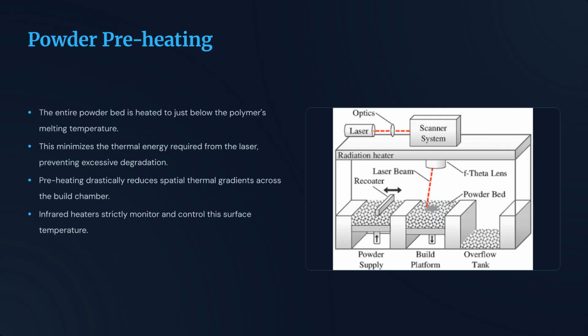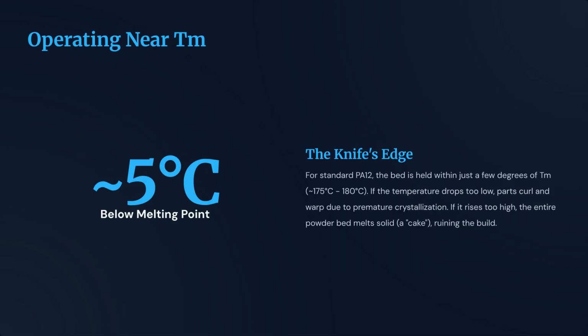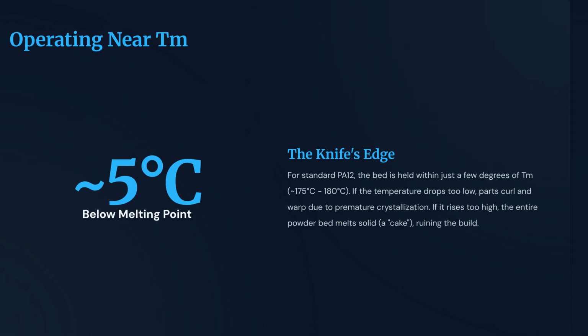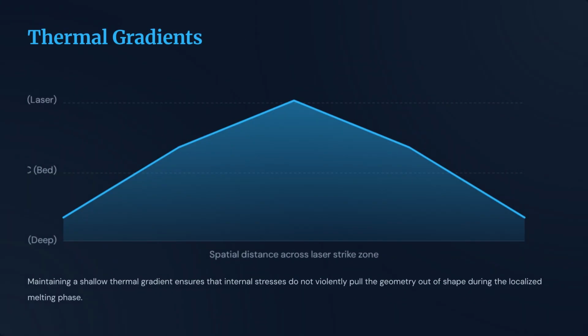Powder preheating is a fundamental step. By heating the bed just below the melting point, we minimize the energy needed from the laser and drastically reduce thermal gradients, which helps prevent warping. Operating near the melting point is a balancing act. If the temperature is too low, parts curl. If it is too high, the entire bed fuses into a solid cake, ruining the build. Maintaining a shallow thermal gradient is key.